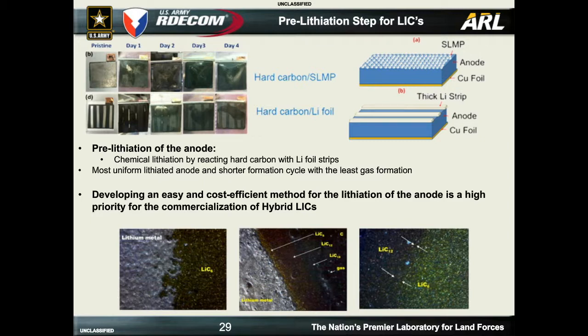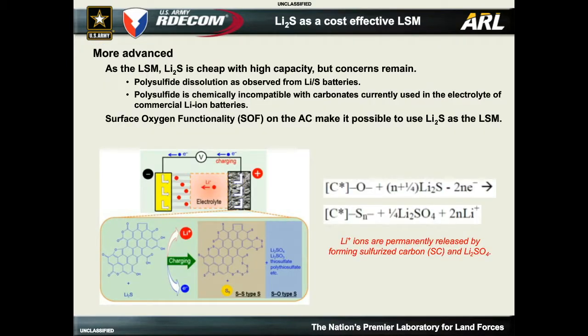So the third approach is to have a sacrificial electrode, so you can have a third electrode essentially, a lithium metal to lithiate that hard carbon. But again, all of these techniques add cost. So we thought about different ways to approach this. And one approach that Sheng Zhang came up with was to actually use lithium sulfide. In this approach, you're putting lithium sulfide into the activated carbon electrode.